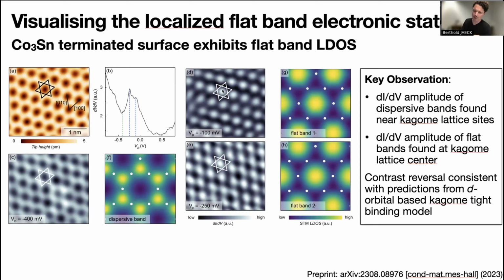To understand this phenomenology, we have been setting up a basic tight binding model, which is spinless, but comprises all the d orbitals per lattice site, where the atoms are now shown here as white dots. Interestingly, when you look at the dispersive band, so I think this is now the dxy, dxz band, we find that the local density of states, in a way, is located between the atoms on the lattice structure rim, and in a way reproduces this honeycomb pattern that we both detect in the mapping experiments, but also the topography. In other words, what we're basically doing here, when we map outside of the flatband, is to visualize the dispersive electronic states whose spectral weight resides at the atomic lattice positions of the cobalt atoms.